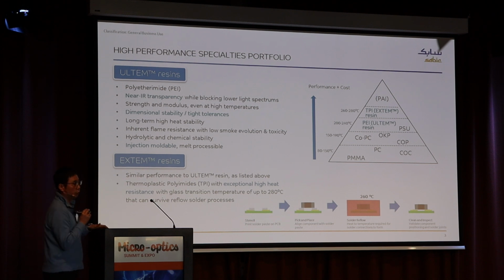The uniqueness of this material is it contains all the benefits of the other EXTEM resins. So it's injection moldable, and it has extremely high temperature resistance up to 280 degrees. So you can use this material for reflow soldering. In the electronics industry, all the electronic components are placed on the PCB. It goes through a reflow oven, and in the reflow oven, temperature can go up to 260 degrees. That is the industry standard. Quite often people think, okay, thermoplastic at that high temperature will melt down. But that's not really the case. So we have IR transparent, injection moldable, reflow capable materials.